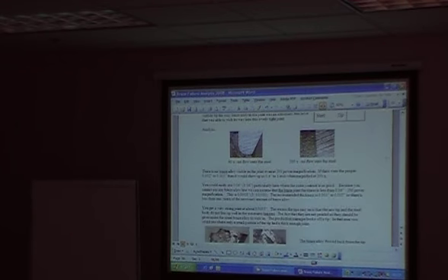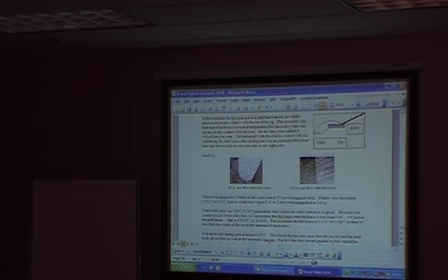Braze failure with an automatic brazer. This is systematic. Here you can see, this is 100x magnification. There's supposed to be 3 to 5 thousandths of an inch there. There is absolutely no braze alloy in that joint at all. We think that the guy who made these saws was saving about $50,000 to $100,000 a year. And what they had is an automatic brazer.